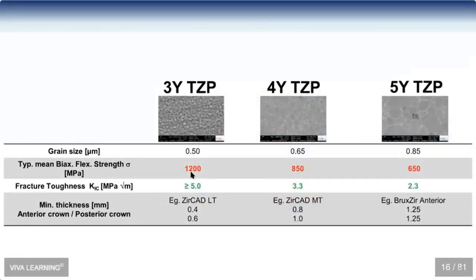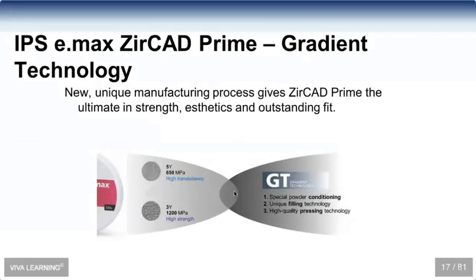If you look at the full strength 3Ys, fracture toughness numbers greater than 5, which is kind of amazing. And with the 4Y, you see it drop to 3.3, and then the 5Y, you see it drop to 2.3. And there are now translucent materials where the entire crown is being made out of this 5Y material as well. But with that 2.3 fracture toughness number, now you're knocking on the door of the fracture toughness of Emax. So it's kind of like, well, why not just use Emax instead of those materials? And that's kind of where I've always fallen.